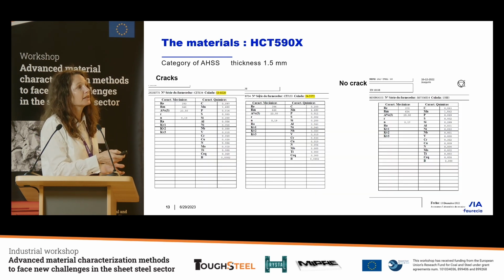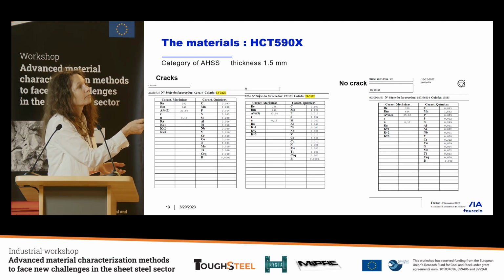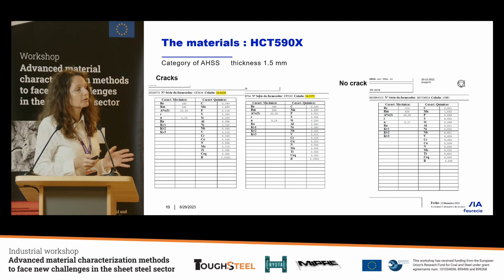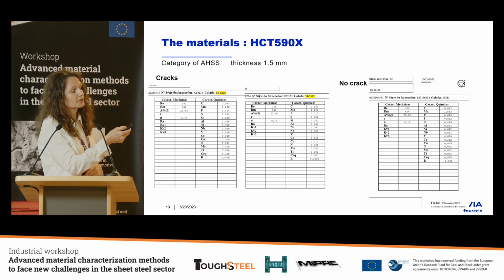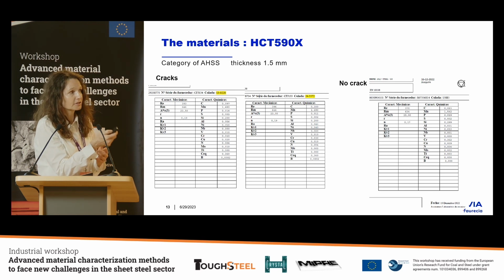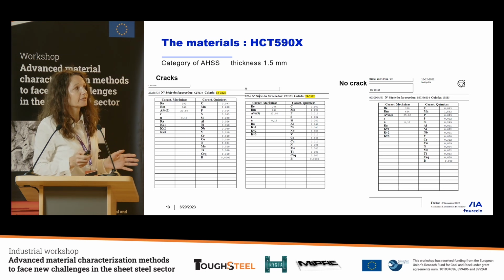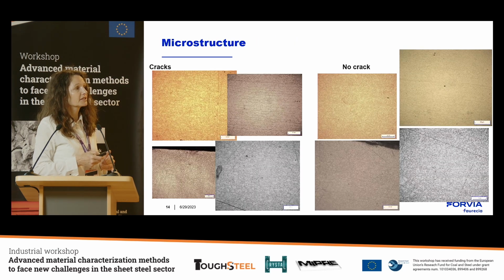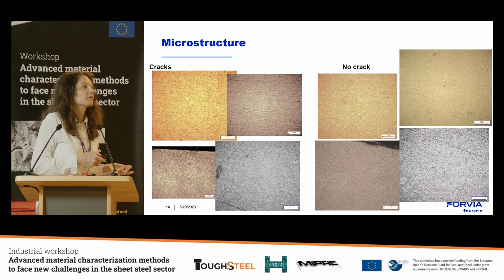Because when we investigate the material certificate, all is the same. In fact, we have the certificate for the cracked material and for the material which doesn't lead to cracks. And regarding chemical composition and mechanical characteristics, it's the same. And even with the examination of the microstructure, it's quite impossible to predict that one material would lead to cracks and the other no cracks.